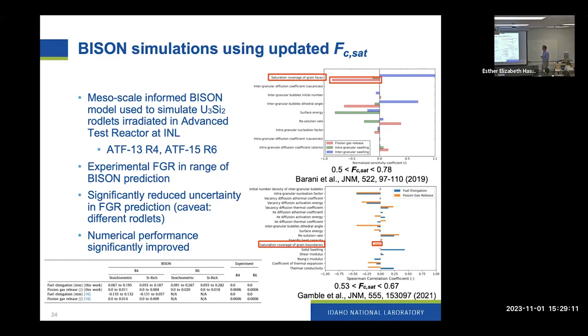One thing I wanted to highlight in particular is that we were able to reduce the uncertainty. This uncertainty or sensitivity analysis was done prior to our mesoscale work, and you see that this was one of the greatest sources of uncertainty in the model. Now, with the caveat that this was a different set of Bison simulations, if you look at the relative contribution to uncertainty from this parameter, now that we've been able to narrow it down, going minus 2 sigma and 2 sigma above the mean value that we found, we've reduced the uncertainty associated with that parameter quite a bit.